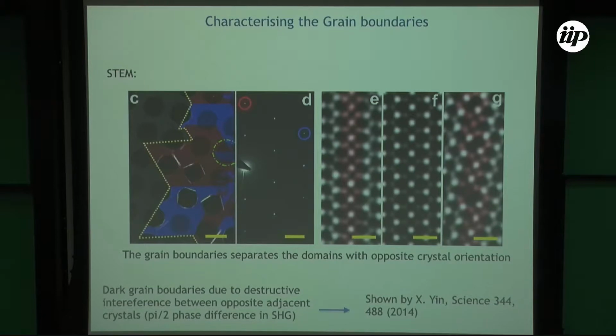But then we decided to investigate the second harmonic coming from these samples a little bit more. In order to characterize what kind of grain boundaries we have, this is a STEM image. In red is one grain, and in blue is another grain of your sample. They are rotated by 180 degrees relative to each other. There's a grain boundary here between the blue region and the red region. Then we zoom in to where the grain boundary is located, and we have this image. You can see that it's a 4|4 grain boundary. It's called a twin grain boundary. It forms when you have this rotation of 180 degrees between the grains. This grain boundary is not perfectly flat, so we have some other defects also.